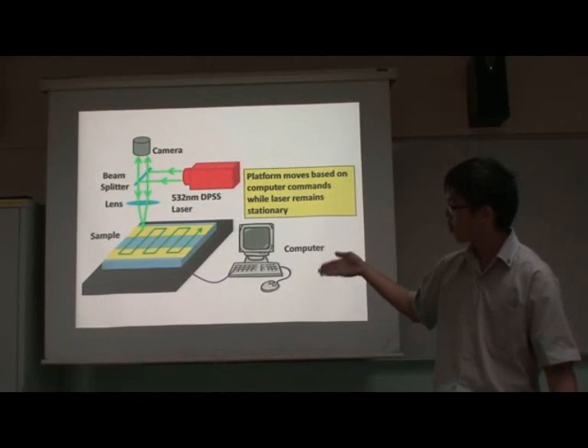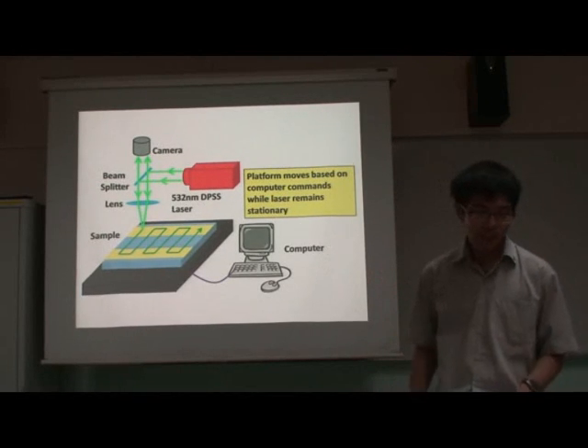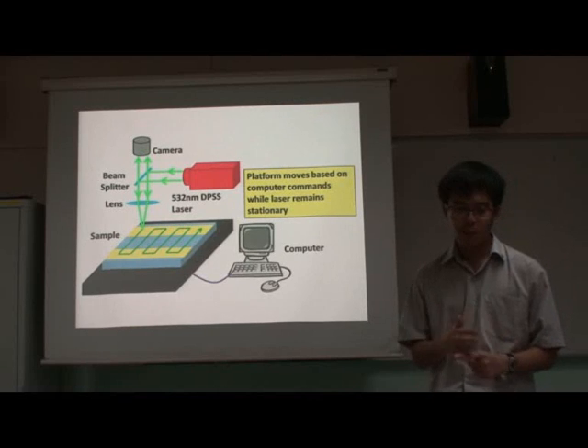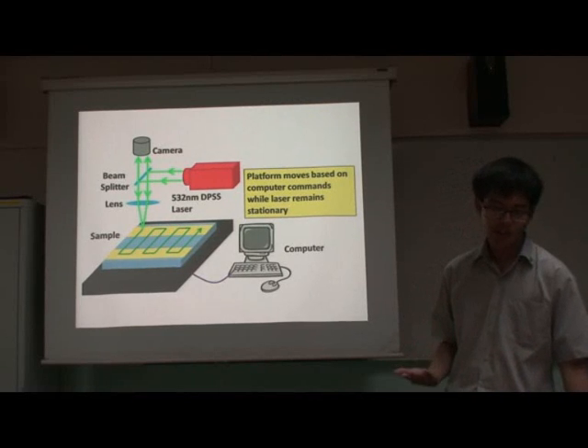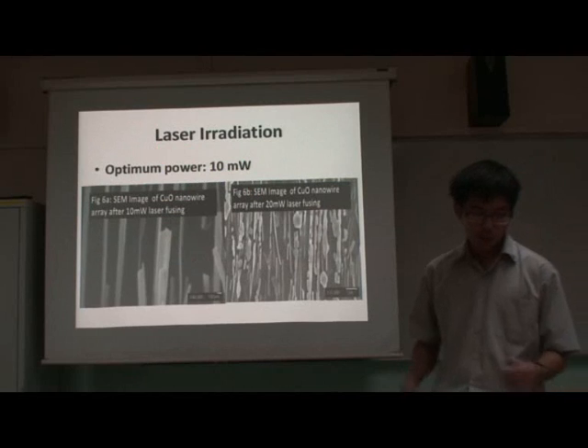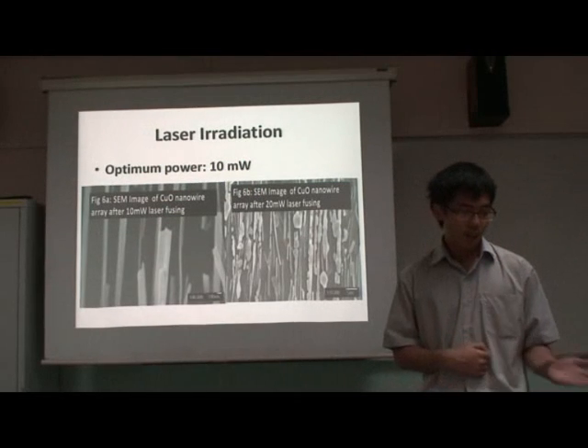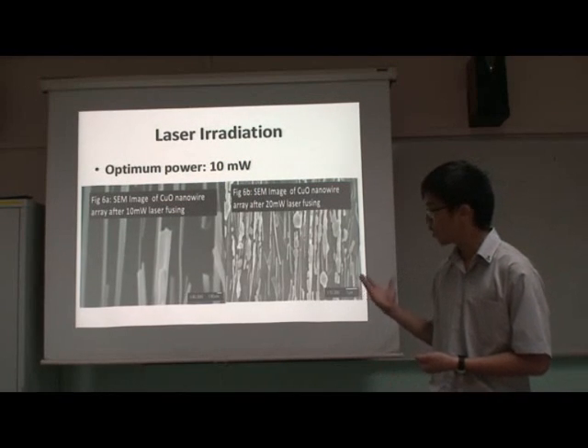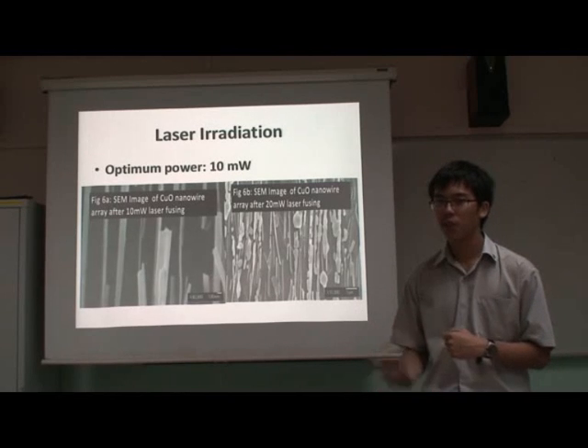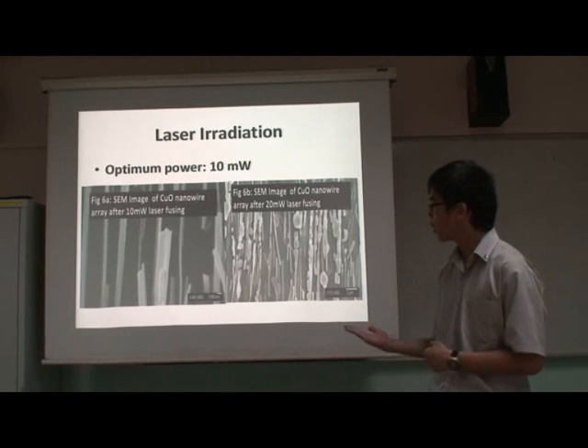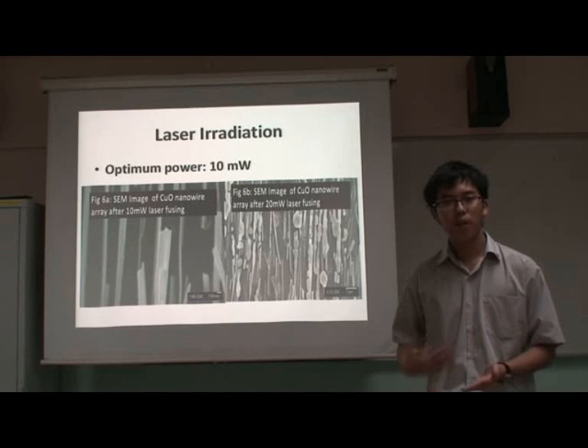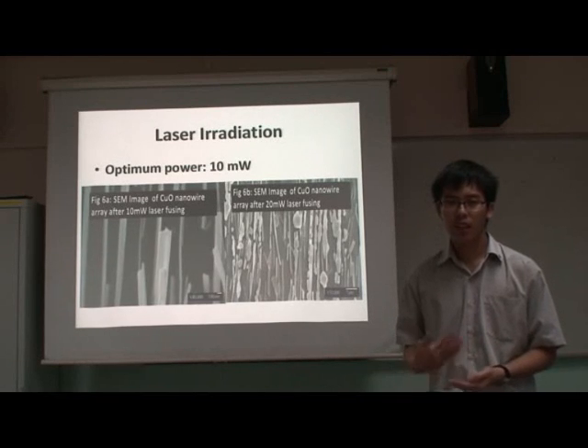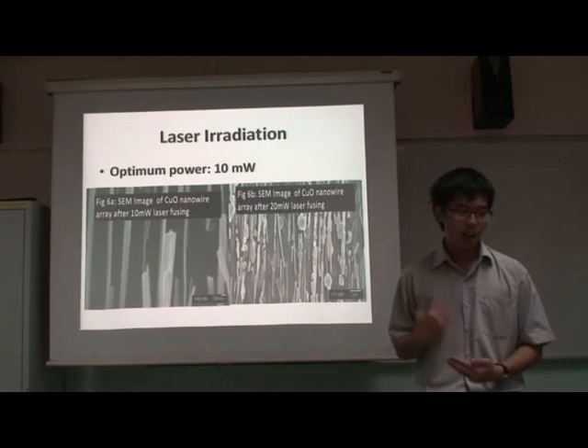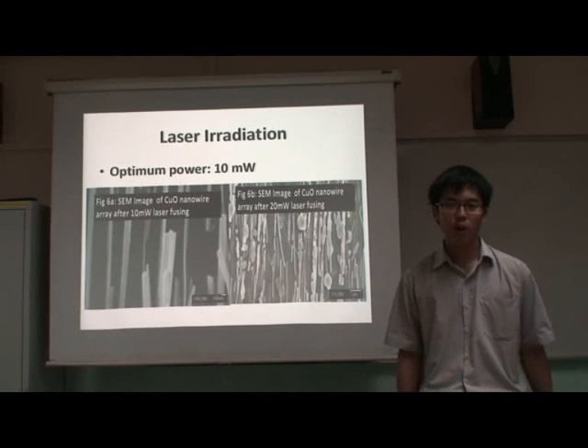The laser will scan parallel to our samples, preventing our nanowires from being cut, which would increase our contact resistance instead. We chose to work with a power of 10 mW, as a higher power would cause the entire nanowire to melt and increase contact resistance instead. After laser irradiation, we will then move on to another round of electrical property testing for comparison. I will now pass it on to Megan to talk more about our results.